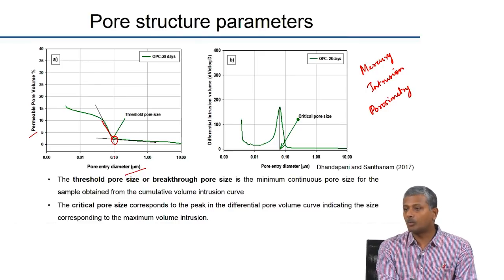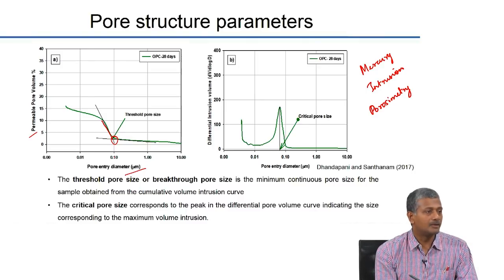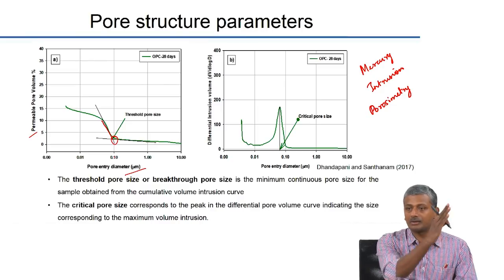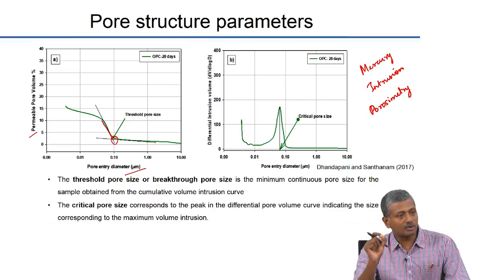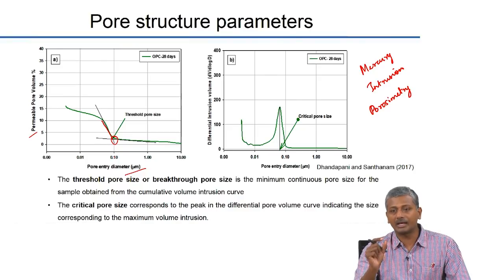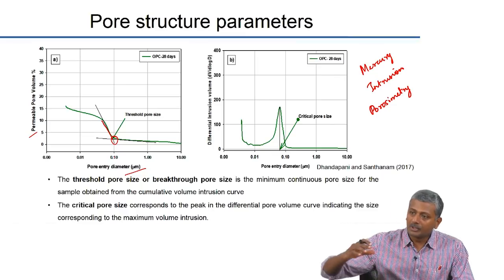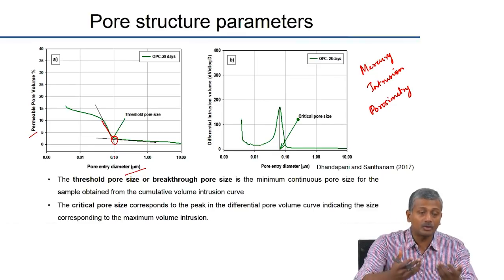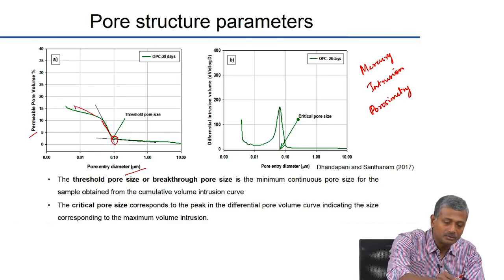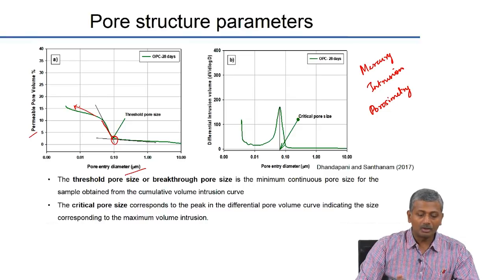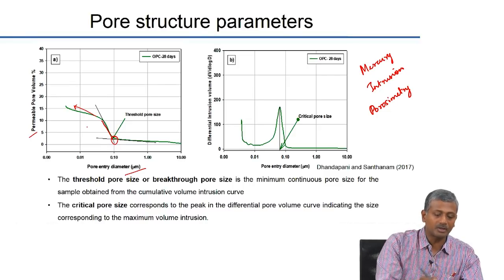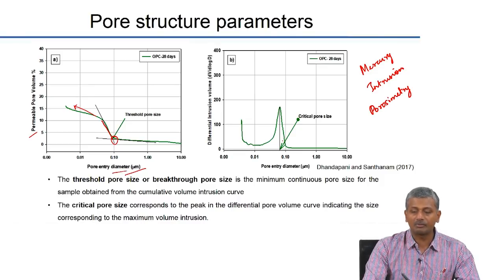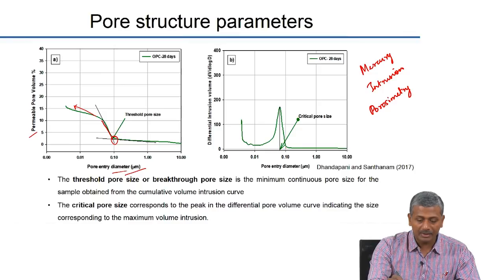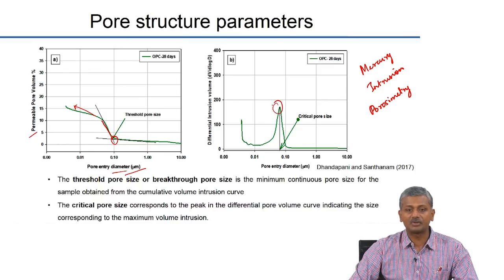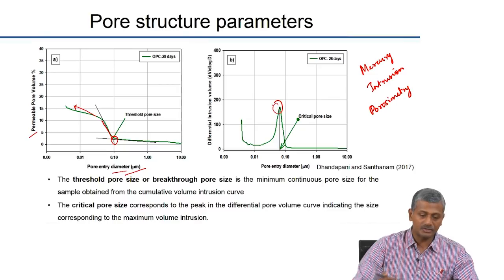No, sorry, 100 nanometer. 0.1 micron is 100 nanometer. So, at 100 nanometers, you see a sudden intrusion which increases. That means that size of porosity is somewhat of a threshold diameter which needs to be overcome for the mercury to penetrate a larger pore system that exists beyond that pore. Okay. And then you again have a gradual change in the volume of penetrable porosity. Now, if you look at the differential plot, you take the same plot and differentiate it with respect to the diameter, you get this kind of a plot. And from here what you can actually get is the critical pore size that you have in your system. That means what sized pores are present in the maximum quantity in your system. So, that is your critical pore size.